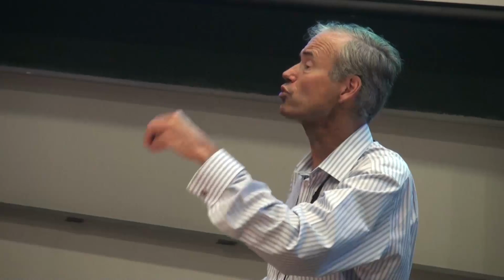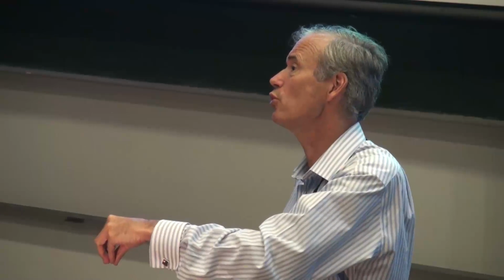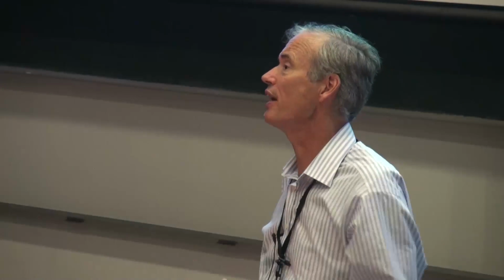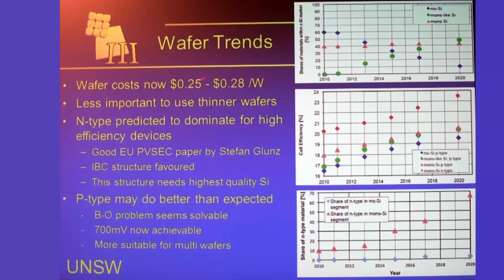So all those three areas we're seeing big improvements, but we're also seeing a lot of downward pressure because of oversupply. There's a big oversupply at the moment in terms of the silicon wafers. And that is also helping push the price down to values that are probably lower than what is sustainable at the moment. So probably sustainable values here would be something more like about 35 cents per watt. But the technology is continuing to improve. So it's only probably 6 to 12 months before these actually become the real sustainable costs for the industry.